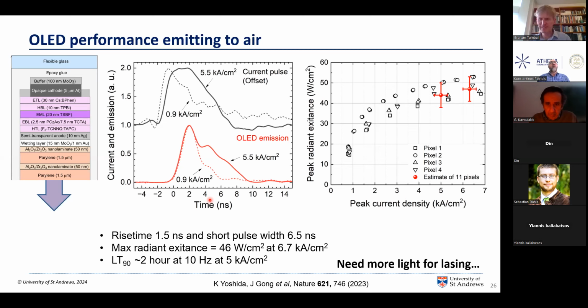Thank you. And you have never tried to pump, in order to lower the losses to the triplet state, to use femtosecond laser pulses, because you mentioned nanoseconds? In other experiments we've in particular been looking at strongly coupled microcavities, strong light matter coupling to make polariton lasers, and those we so far have always used femtosecond pumping. If the rise time of the pump pulse is of order 1 nanosecond, then it's okay. If the rise time of the pump pulse is of order 10 nanoseconds, it's less okay.